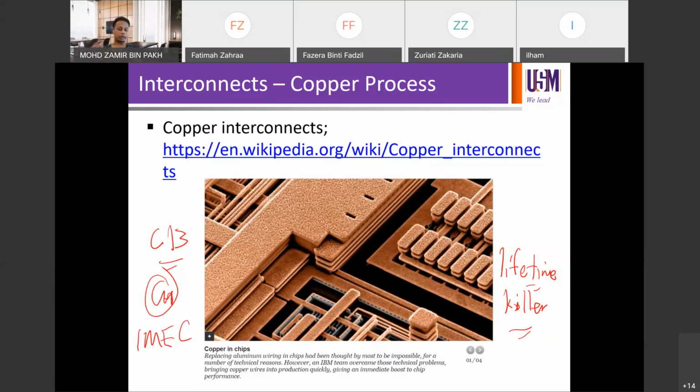So we had to allocate a different time. And when I was an EE back then, an equipment engineer, after running a copper lot, we had to stop the equipment and decontaminate the whole equipment, doing the cleaning for like 1-2 hours to make sure that every single module in the track process, so hot plate, cool plate, coater, developer, WEE, EBR, what else? Robot arms for all the regions need to be wiped cleanly, and then we had to run hundreds of test wafers before we release to mass production.